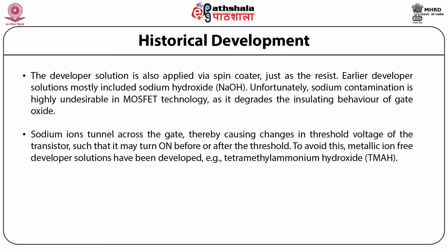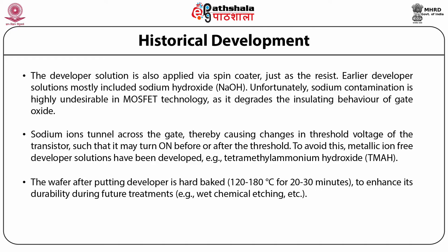To avoid this, metallic ion-free developer solutions have been developed using tetramethyl ammonium hydroxide. The wafer after applying the developer is hard-baked to enhance its durability during future treatments.